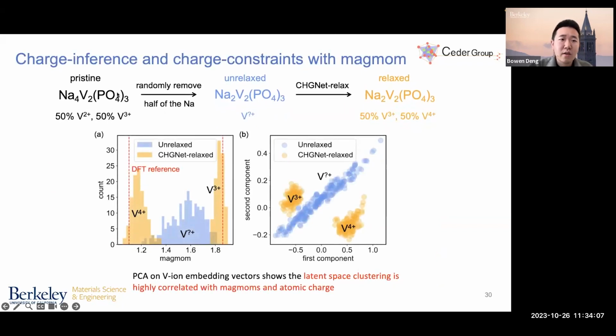If you calculate the oxidation state simply from the change of composition, since we know that the sodium ions, the P and O do not change their valence states, you can estimate that the vanadium ions will be oxidized from 50% vanadium 2+ and 50% vanadium 3+ to 50% 3+ and 50% 4+. But the tricky problem is: how do we know which of these vanadium ions are 3+ and which are 4+? How do we know where the charge transfers to? We use CHGNet to calculate the magmoms on the unrelaxed structure and the relaxed structure, the blue one and the orange one. On the left plot, we show the vanadium magmoms are well separated into two peaks after the relaxation. The two orange peaks correspond to vanadium 3+ and vanadium 4+, which were formed with ionic arrangements that break the symmetry.